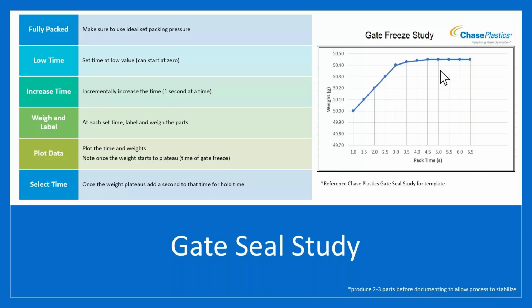or your one cavity is going to be significantly behind in terms of the volume or the velocity it was filled at, and ultimately the melt temperature in the cavity. So, what you do for a family tool is you have to optimize for first to fill. So, instead of using the 95 to 98 on your single part or on your same geometry across the board, you apply that to your first to fill cavity. But what about valve gates? Valve gates are an entirely different animal there as well because you don't have to freeze that gate. You're going to mechanically close that gate.